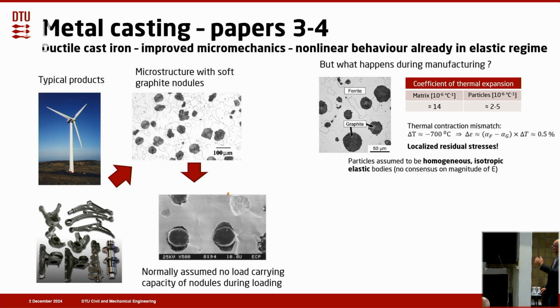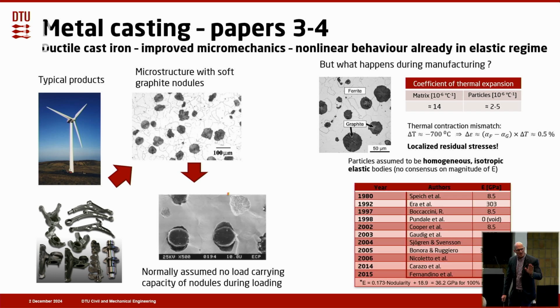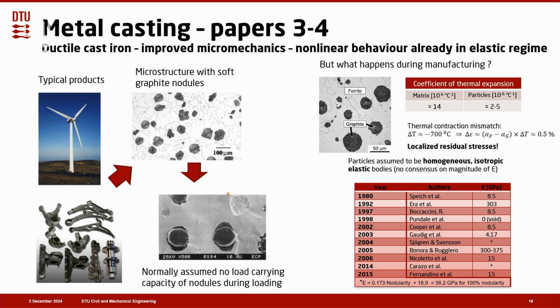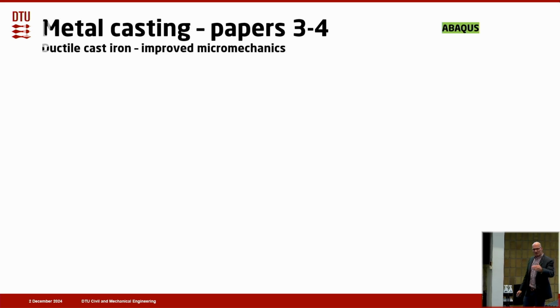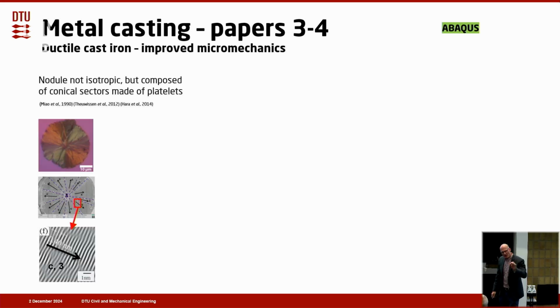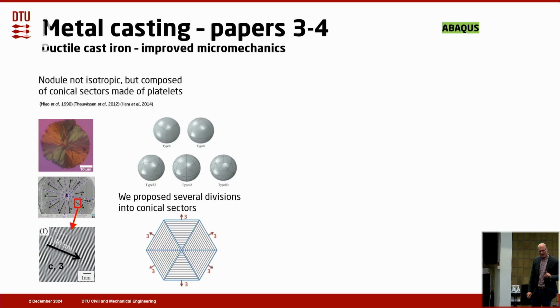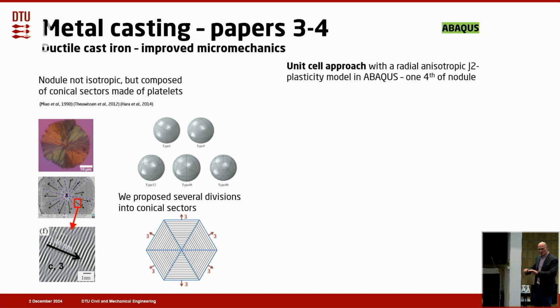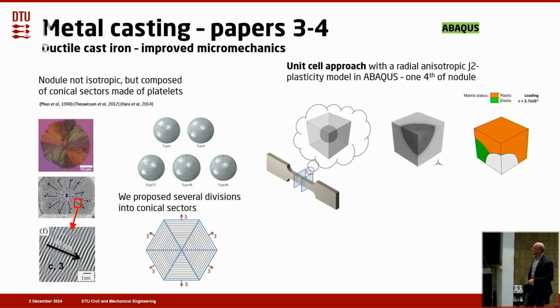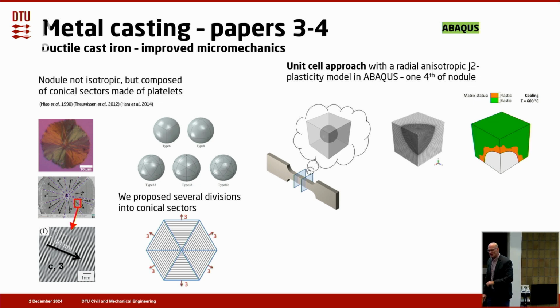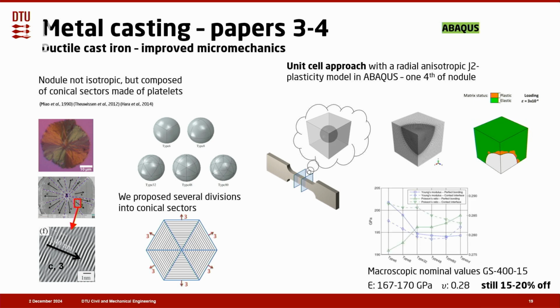So people would normally look at those as homogeneous isotropic elastic bodies, but there was absolutely no consensus in the literature as to how to model the Young's modulus. You see it goes from 0 to a lot, and that's a big variation, I would say. So what we did was that we looked into the literature and had a look at those nodules. We found out they're not isotropic, but composed of conical sectors made of platelets. And then we proposed several divisions into conical sectors. And then we did a unit cell approach. This was our first model. And then we could do something like this, where you have elastic and plastic deformation in a unit cell approach. And then we could predict some macroscopic nominal values for Young's modulus and Poisson ratio. And it was still 15 to 20% off. So we were on the right path.